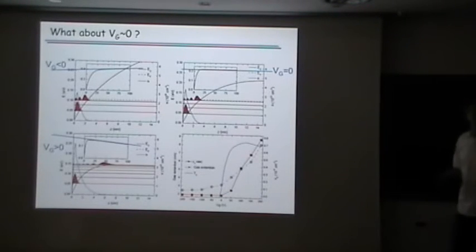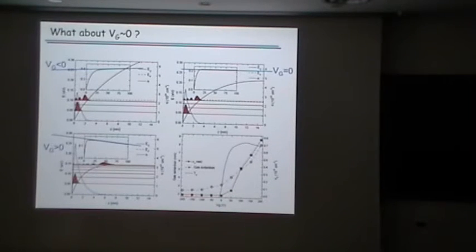In fact, when you cool down, the system arranges itself in the number of carriers such that the Fermi level is just at the top here. Then, when you gate too much in this system the first time, you cannot put more electrons. They just go back, I mean, go in this direction. This is maybe also the reason why nobody is able to close the superconducting dome. People try to put more and more carriers to go beyond this number, but there is a limit. I think this is a trivial limit here.